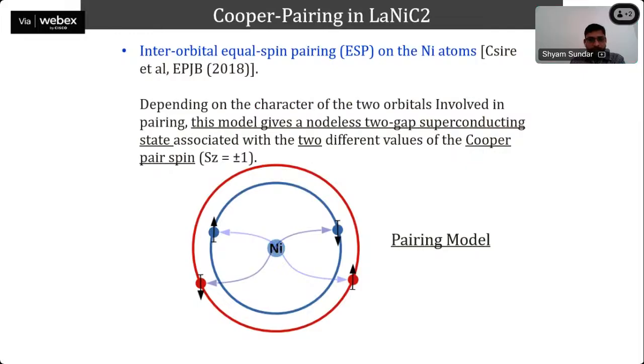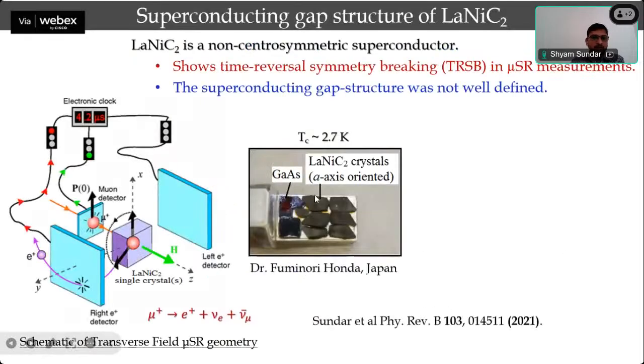To find this experimentally, we planned these muSR experiments. We got these single crystals from our collaborator Fuminori Honda from Japan, and these are the LaNiC2 crystals, a-axis oriented. These are on gallium arsenide to suppress the background contribution. They are mounted on a silver plate which doesn't have any relaxation, so there is no background contribution to the relaxation. That's why we use this silver plate.